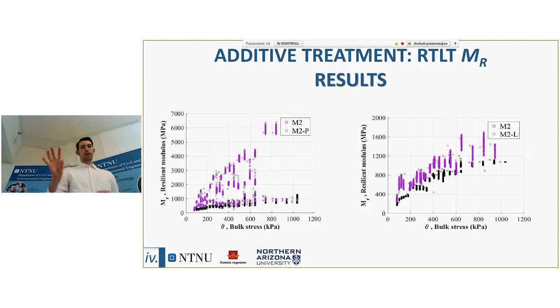One part portrays the results with the lignin, and the other part of the slide deals with the results connected to the use of the polymer-based additive. So here, for example, let's start with presenting the experimental data coming from the repeated Tri-axial test. It's very clear that the experimental data connected to the magenta color, to the treated rocks, are much higher than the data connected to the untreated rocks.